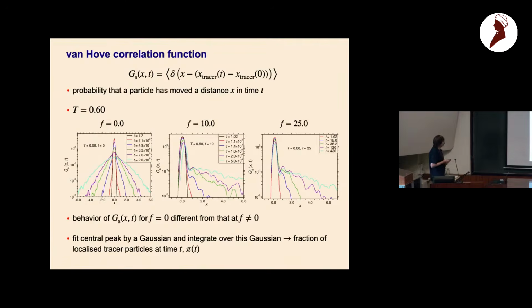One can also consider the Van Hove correlation function, now at low temperature in comparison to the equilibrium system, at F equal 10 and F equal 25. There you see very pronounced localized particles - this is the central peak - and then at long times, the very mobile particles, reflected by these tails.